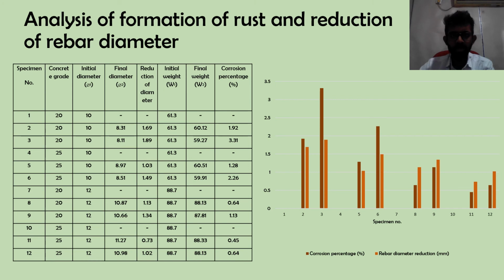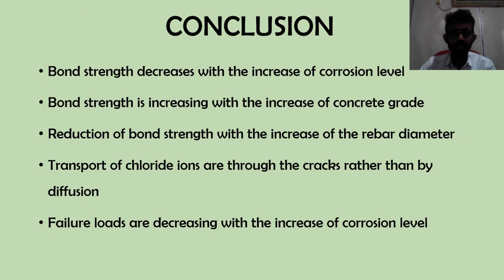Let us move on to the conclusion. Conclusion. The bond strength decreases with the increase of corrosion level. Also, the bond strength is directly proportional to the concrete grade, whereas the bond strength is increasing with the increase of concrete grade. Furthermore, the effect of rebar diameter on the bond strength reduction can be seen in all corrosion levels, and there is a significant reduction of bond strength with the increase of rebar diameter.